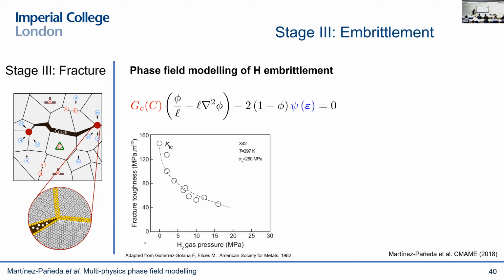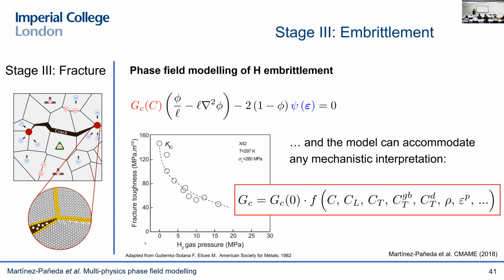calibration whatsoever. So my plan here was to come up with a mechanistic hydrogen degradation function that incorporated the underlying physics. And I'll explain in a minute what my idea is, what is happening in there. But I think the good news is that this framework is universal. So whether you agree with me or you have other ideas on how to define this hydrogen degradation function, you can always define it as a function of any micro or macromechanical parameter that you consider of interest. And other groups have taken our model and expanded it in other directions.